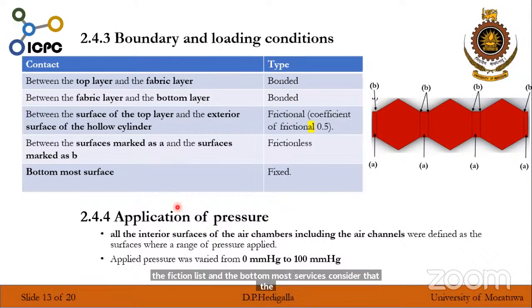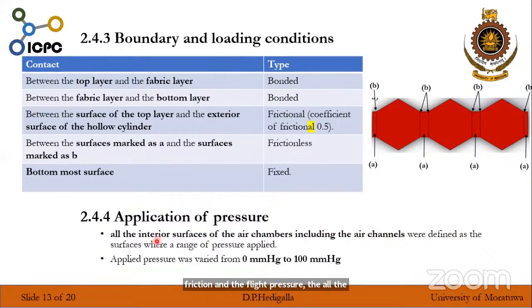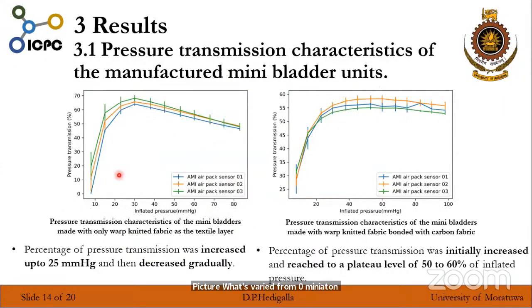And for the applied pressure, all the interior surfaces of the air chambers, including the air channels, were defined as the surfaces of applied pressure, and the applied pressure was varied from 0 mmHg to 100 mmHg. And here are the results. As you can see here, these are the pressure transmission characteristics of the mini bladders. Here, the pressure transmission was initially increased and then gradually decreased. And here, the pressure transmission was initially increased and reached a plateau level.